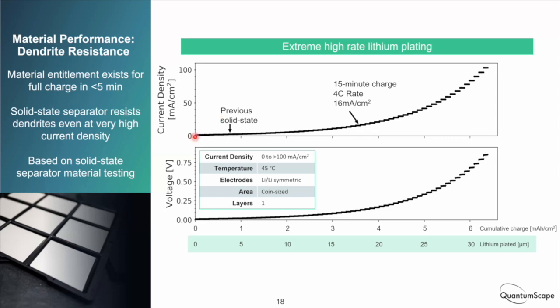So we're passing small amounts of lithium and then increasing the current density, passing more lithium and increasing the current density, and continuing to increase it here. Many solid state efforts could do south of 1 milliamp per centimeter squared, or up to about 1 milliamp per centimeter squared. To get to the 4C charge rates that I described earlier, that's 12 to 16 milliamps per square centimeter, depending on cathode thickness. We went all the way to north of 100 milliamps per square centimeter across the separator without failure.